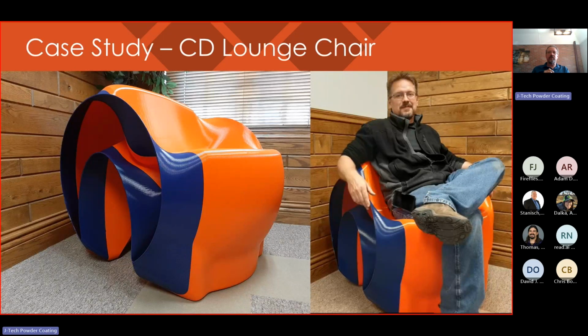And total print time was about 12 hours, printed with PETG filament. Material cost for this piece is about $300. We plan on printing another version of this with our 3mm pellet extruder and recycled PETG or possibly PLA. Material cost in that process is going to be under $60, and the print time should be cut in half, which makes it much more viable from a commercial standpoint.